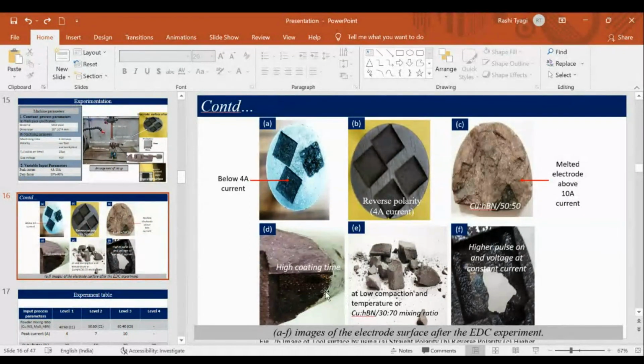It means current goes through the green compact tool and connects with the tool surface that we don't want to deposit. So we have fixed the coating time. There is a low compaction pressure and temperature. If we use a very low compaction pressure, the tool will break. So we have to decide a particular temperature and pressure that we want to use in this process.